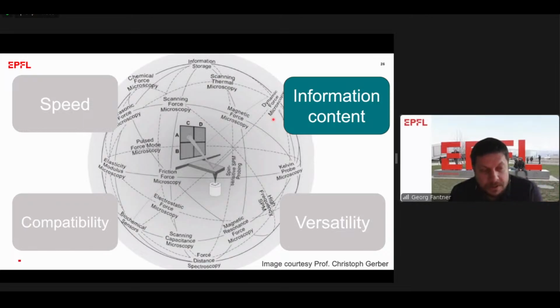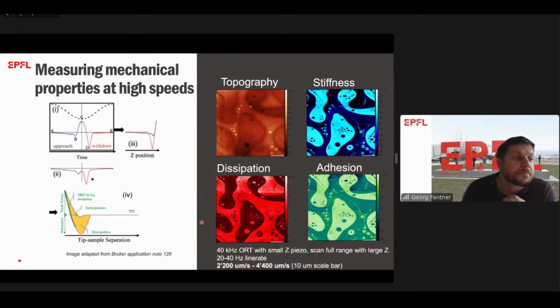All of the work that I've shown you so far was just looking at images, looking at the topography in a very classical way to use the AFM. But because of this off-resonance mode that I explained earlier, we are getting, for each point in the image, de facto a force curve. We get the deflection as a function of time, which we can afterwards turn into a deflection as a function of z position, which is a little miniature indentation curve at every point. And now we can use contact mechanics to get mechanical properties out of this.